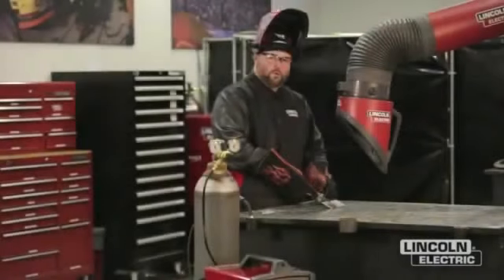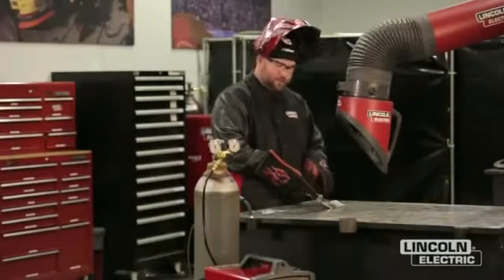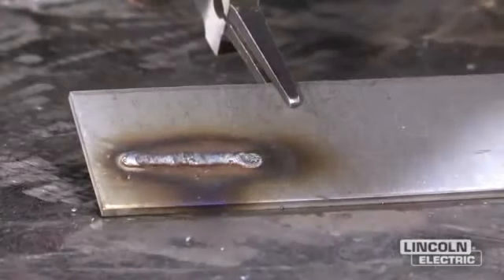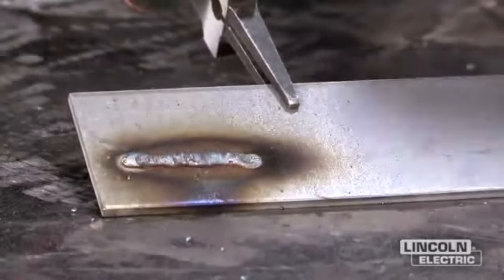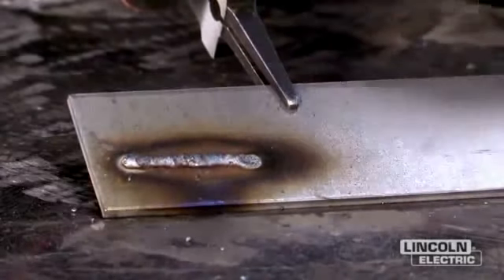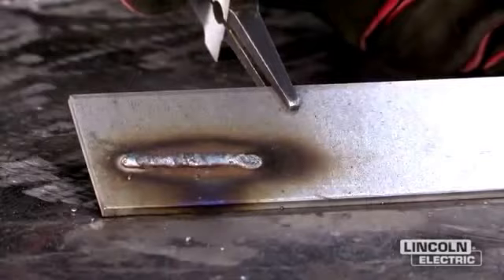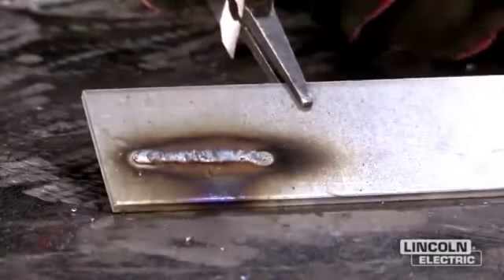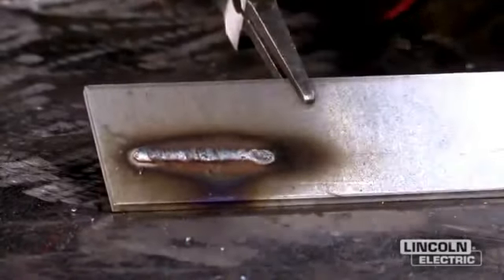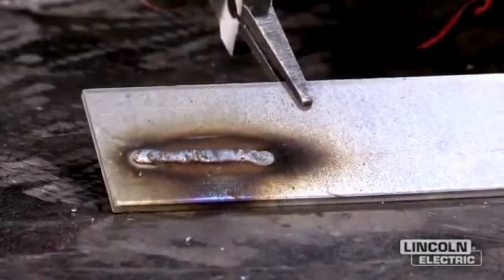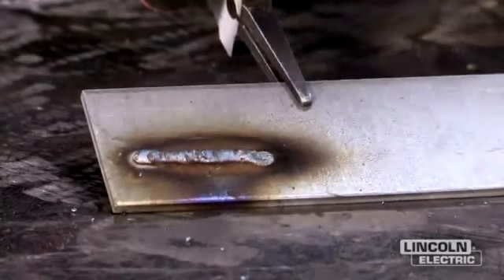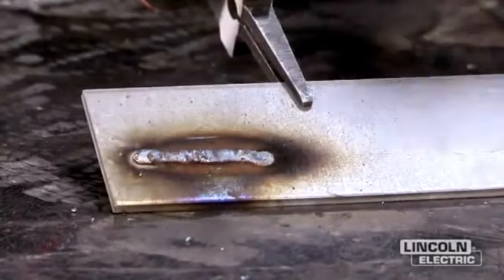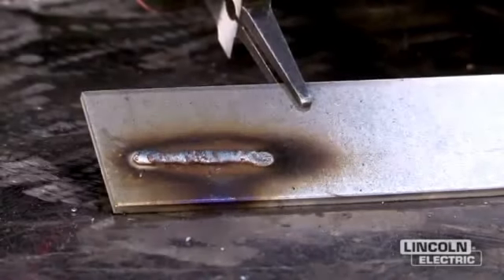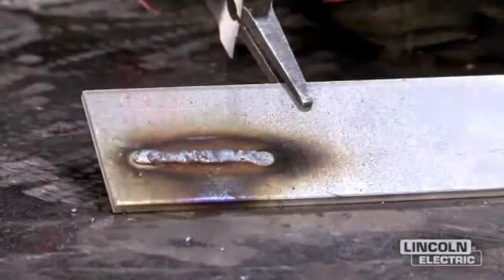So we just finished our weld with not enough shielding gas. And as you can see, there was a lot of spatter and the weld was getting contaminated from the oxygen and nitrogen in the air attacking that molten puddle. So again, you can tell by the amount of spatter, and you also see the pinholes in the crater of the weld. And that's going to tell you to go back, check your gas shielding setup, make sure your connections are tight, and then you can make a good weld.